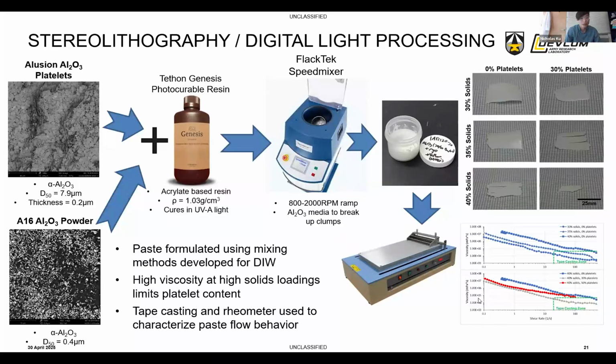But really where we're at right now in stereolithography or digital light processing is creating these slurries, right? We're taking the commercial powders that we have interest in and suspending those in different acrylate-based resins, trying to understand how that allows for curing of this material. Currently we have a tape casting setup to create thin layers of this slurry, and then use a UV lamp to understand how deep it can cure. The more powder you put in, the higher the solids loading, the better it will sinter, but the more it's going to scatter and reduce your depth of cure in your material. So you're playing with that sort of balance.